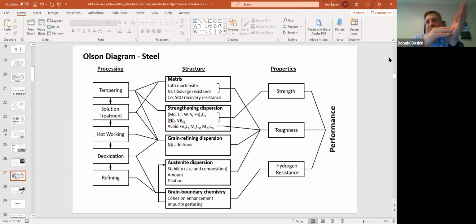You start off with iron ore, that gets refined, the impurities come out, deoxidize. Okay, you have to take the oxides out of it to keep the material strong, to keep the steel clean, to keep the grains attached to one another. Work hardening, increase the dislocation density. Solution treating, like we mentioned, austenitize at 870 degrees Celsius, and then quench, and then temper.